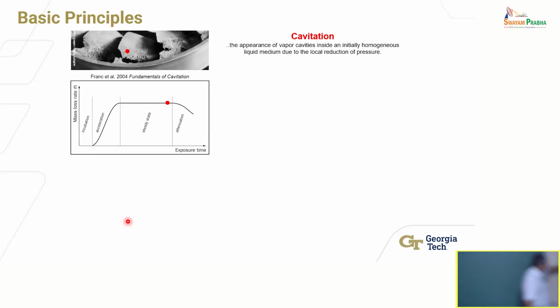So what happens when you subject a solid surface, let's say a metallic surface, to such collapsing vapor bubbles that have been generated somehow in a liquid medium? You have this water stream with bubbles in it, impacting the surface. Though it's not the water impacting the surface that is causing this erosion. It's these bubbles that are collapsing, generating shock waves, and the shock wave and the microjets are strong enough to erode the surface. That's what's happening.